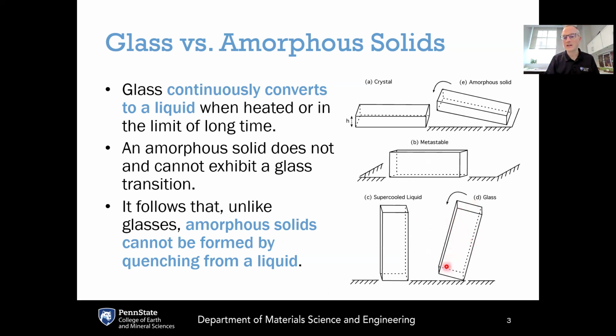So this glassy state is unstable, and it's continuously relaxing towards the supercooled liquid, and that supercooled liquid is in turn metastable with respect to the crystal. So those are the three different levels of stability here: the unstable glassy state, which is going to relax towards the supercooled liquid state, and that is metastable, and when that gets perturbed, eventually it could crystallize.